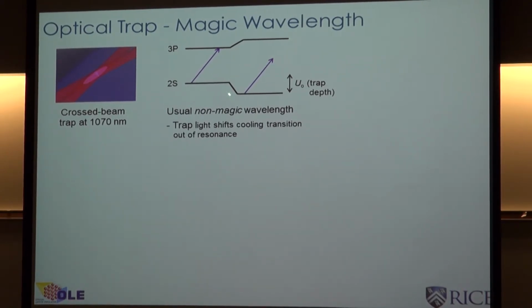We found this only after the fact. There's something called a magic wavelength. The way an optical trap works is that there's a shift in the ground energy level, a light shift due to this off-resonant laser beam. Because the laser beam is red, the light shift goes in the negative direction, and you end up getting a trapping potential. But what usually happens in the usual trap is that at the same time you're shifting the ground level, you're also shifting the upper level. That changes the spectroscopy, and so the cooling doesn't work normally. The MOT cooling would not work in this optical trap.